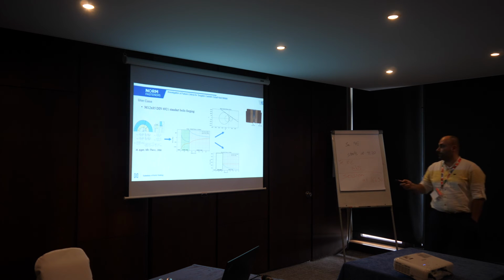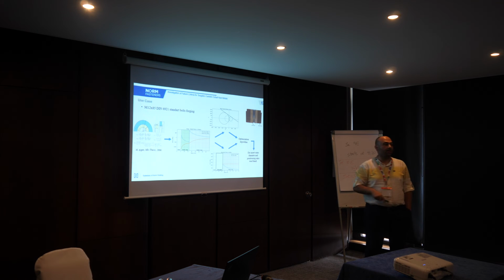So I have the analytic calculations so that I can calculate the hoop stresses and radial stresses. And from hoop stresses and radial stresses, I can obtain the Mohr-Coulomb failure criteria for tungsten carbide-cobalt and the von Mises criteria for the outer ring of tool steel H13. Then I can run my optimization algorithm, and I can find the die insert diameter and the pre-stressing ratio that is keeping my tungsten carbide-cobalt as safe as possible.